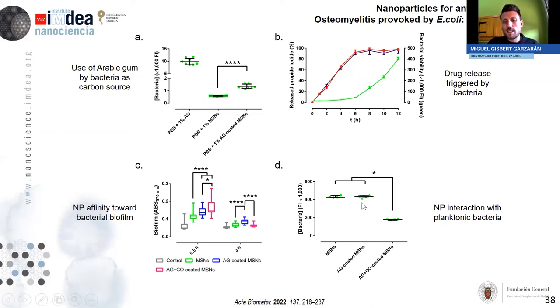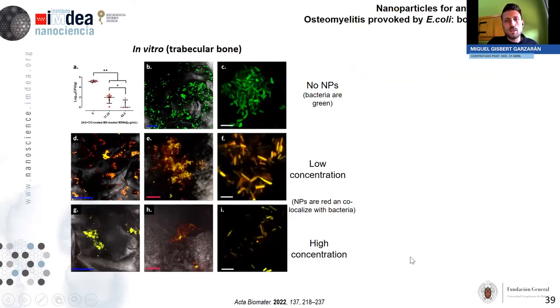Okay, and finally, we did some experiments with planktonic bacteria, which are bacteria that are not in a biofilm state. And we could see that the viability of the bacteria decreased in the presence of the nanoparticles coated with Arabic gum and also colistin, because colistin is also an antibiotic. Okay, so regarding the treatment of the infection, we carried out two different experiments, one in vitro and one in vivo. I will show it later. And we used two models of